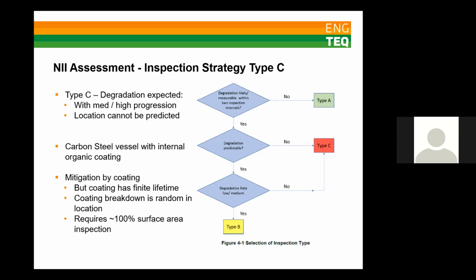So some coatings can fail very quickly, within a year or two, and others could last for decades. But once the coating fails, the carbon steel is exposed and may corrode quickly. So the location of coating breakdown is considered to be random and is therefore impossible to predict. It's not possible to inspect for coating condition, so we must inspect for wall loss in the carbon steel. It is also not possible to estimate what's happening in one location based on another, unlike in a Type B inspection. So if, for example, we were to inspect 50% and find no corrosion, there's absolutely no confidence that there's no corrosion in the remaining 50%. So we must inspect as close as possible to 100% of the vessel. But this could be time-consuming and expensive and is a potential disadvantage, especially in the case of large vessels.